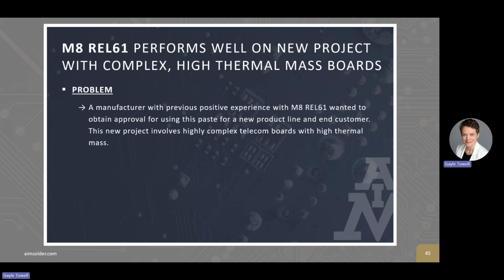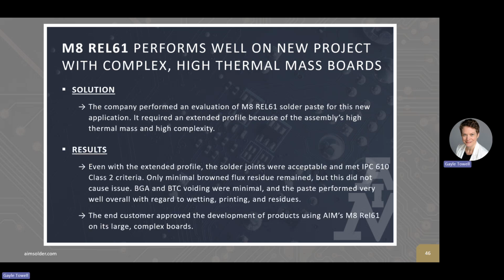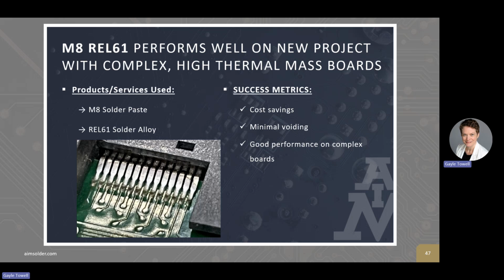As another example, M8 REL61 paste performed well on a new project with complex high thermal mass boards. So a manufacturer that had previous positive experience with this paste wanted to see if they could use it for a new product line. They tried out M8 REL61 on the assembly, and it required an extended profile because of the high thermal mass and the high complexity of this build. So the end result was very good solder joints, minimal residue, and minimal voiding, and they approved the paste for development. So they were able to save costs, they experienced minimal voiding, and they had good performance on what were complex boards.